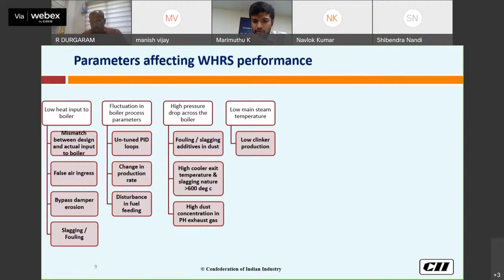So if low clinker production is there, then my heat input is also less, so the temperature will definitely be less. And low cooler exit temperature: if my cooler exit temperature itself is less, for example, instead of 400 I designed my main steam temperature to be 350, then my main steam temperature will not be 350. So this is also one contributing factor.